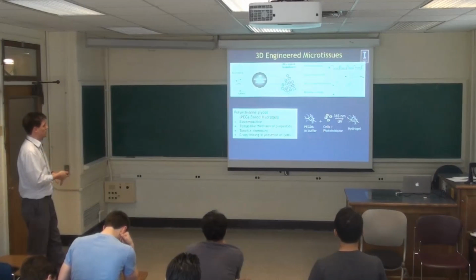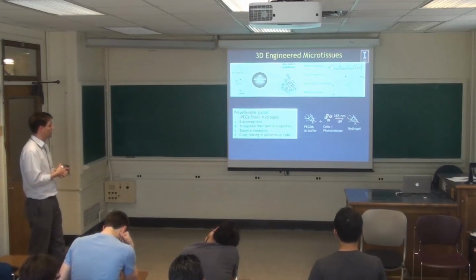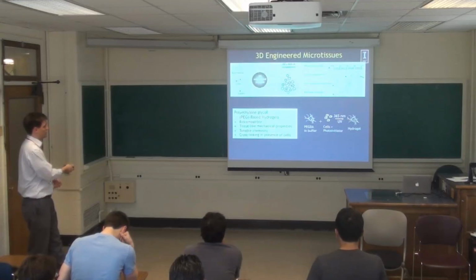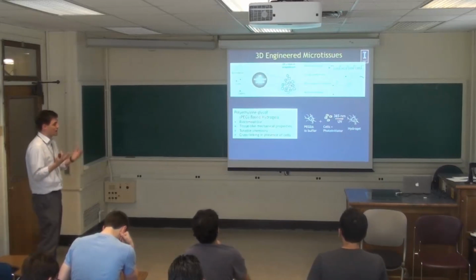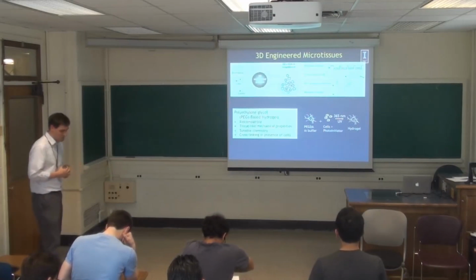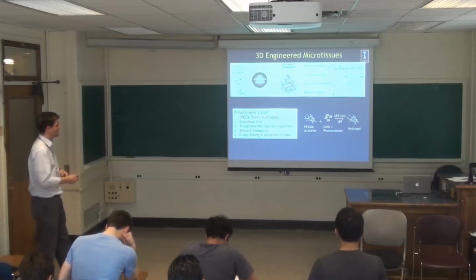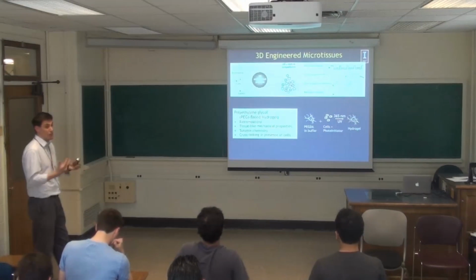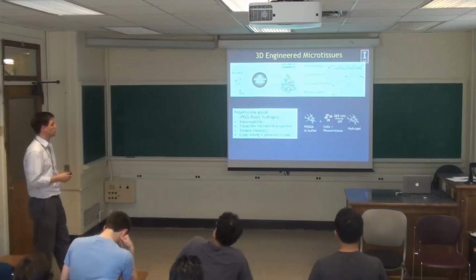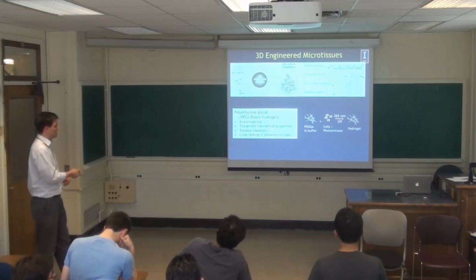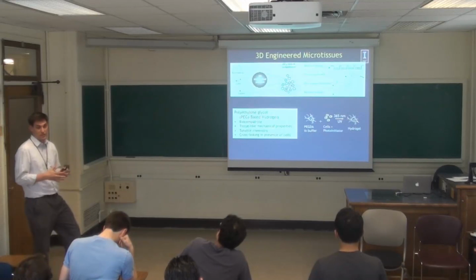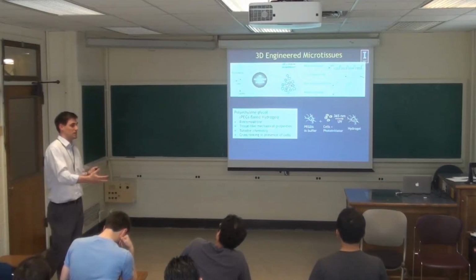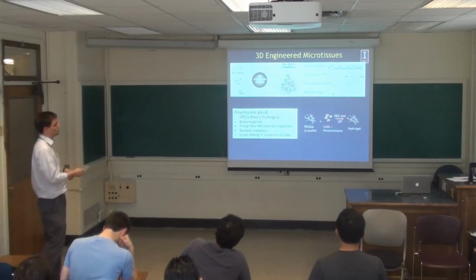The examples I want to show today are we were using polyethylene glycol-based hydrogels or PEG-based hydrogels. There are various reasons why those are very commonly used in tissue engineering and three-dimensional models illustrated here. They're biocompatible. They have very high water content, so they have very tissue-like mechanical properties, and they're very tunable. So it's essentially a synthetic blank slate that you can modify in any way that you want.